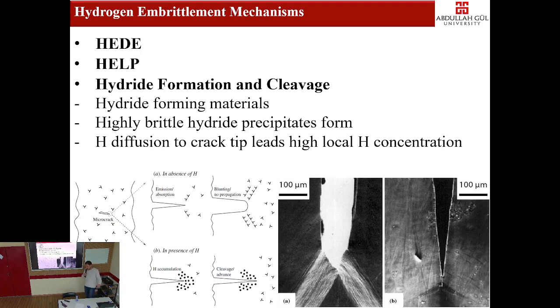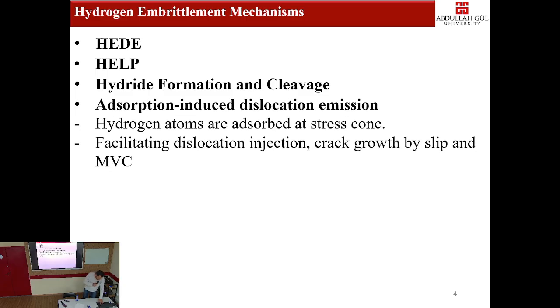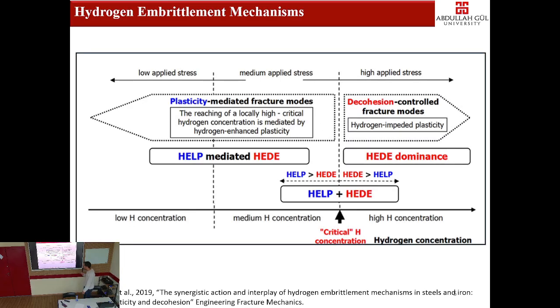If the hydrogen to metal ratio is greater than 0.1, hydrogen tends to become hydride at the crack tip, and it causes some blunting, and we see adsorption induced dislocation emission. Depending on the hydrogen concentration, we can also observe the coexistence of different hydrogen embrittlement mechanisms. So the real question is, it is still unknown what hydrogen causes at the molecular scale and microscale, and the interaction of hydrogen with dislocations is the real question to uncover the micromechanism or molecular mechanism of hydrogen embrittlement.